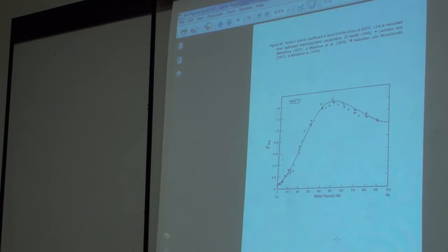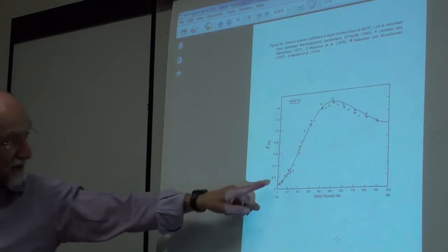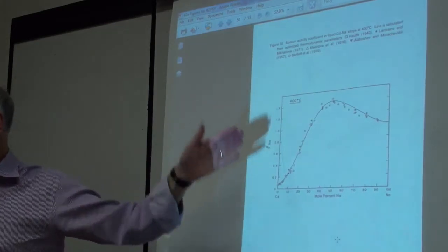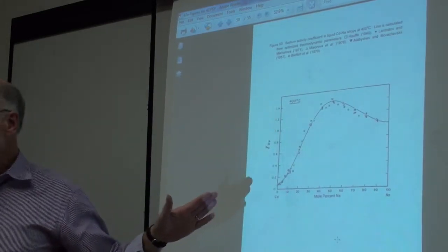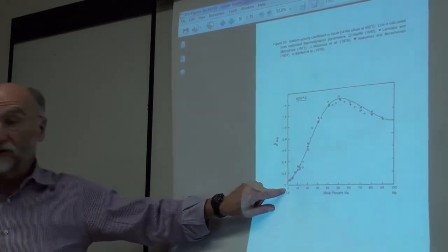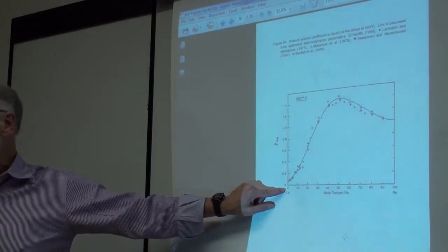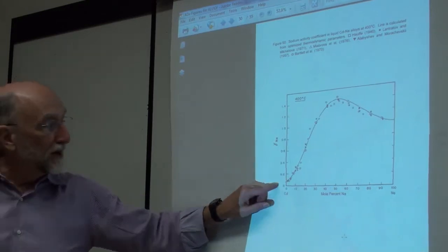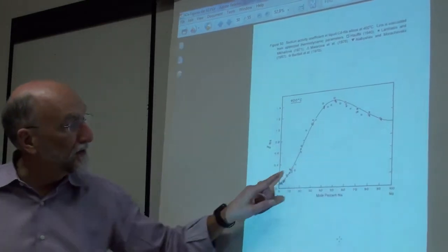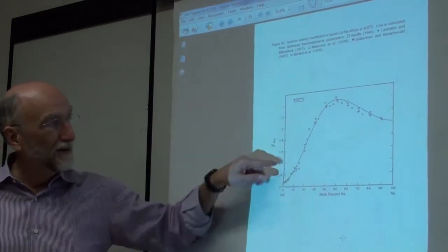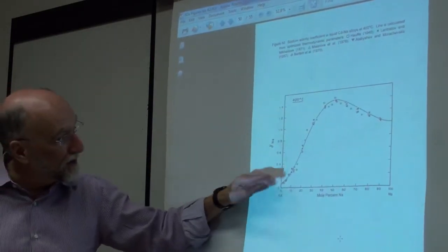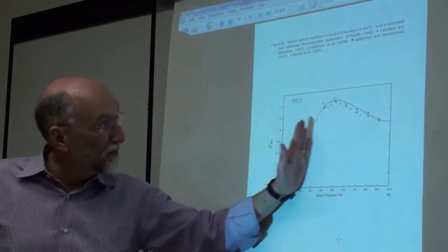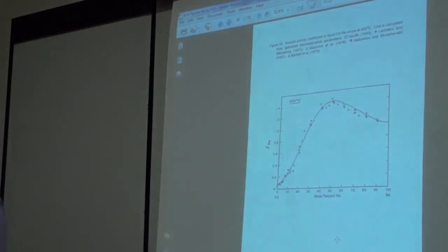Remember now that the activity coefficient of sodium has been measured over the whole composition region. So in principle, the activity coefficient of cadmium is obtained. You can fit this up, and you'll get the activity coefficient of cadmium. And you do have your endpoint. It goes all the way to pure cadmium, where gamma cadmium is known. So you have your endpoint for your Gibbs-Duhem integration. But remember that you're integrating back from this point, so your activity coefficient of cadmium is not going to be as accurate as the activity coefficient of sodium, because you're integrating from the slope of this curve. And the closer you get to pure sodium, the less accurate will your activity coefficient of cadmium be. So just keep that in mind when you're interpreting your final results.